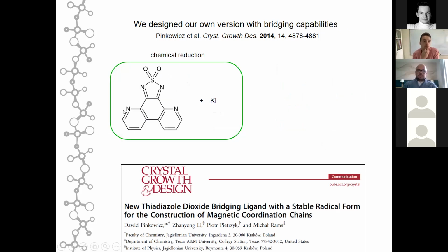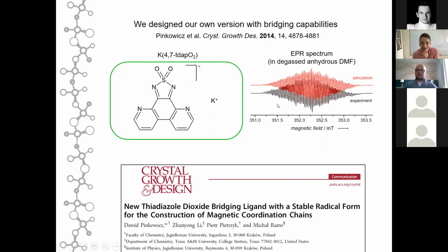So, as I said, this 4,7-phenanthroline dioxothiadiazole can be easily reduced using potassium iodide, and here is the EPR spectrum in degassed anhydrous DMF. You can see it's quite complex because you can see the coupling with the nitrogen and hydrogen atoms of the molecule. And we actually managed to calculate the spin density on the different nitrogen atoms. It appears that the spin density on these two nitrogen atoms of the dioxothiadiazole moiety is quite high, 0.25 per nitrogen atom. On these two 4,7-phenanthroline nitrogen atoms, it's a little bit lower, 0.1, but still quite high, and should be useful to obtain molecular magnets with quite strong coupling with magnetic centers.